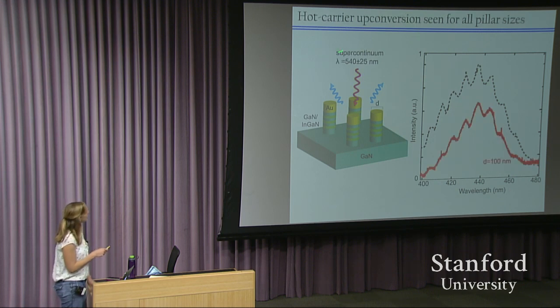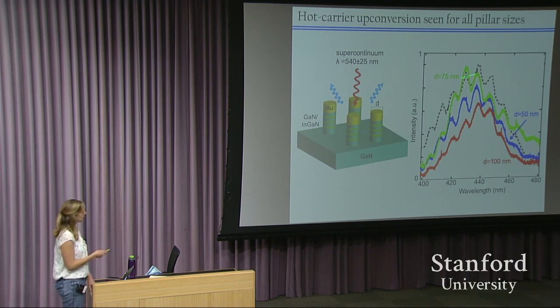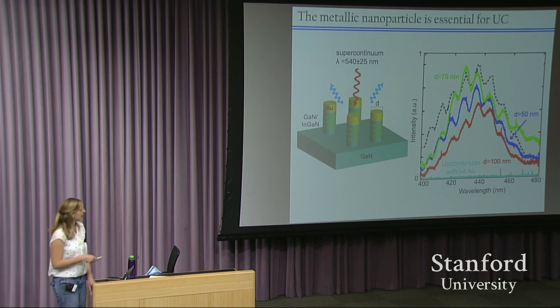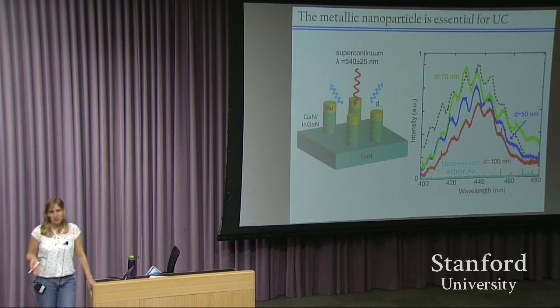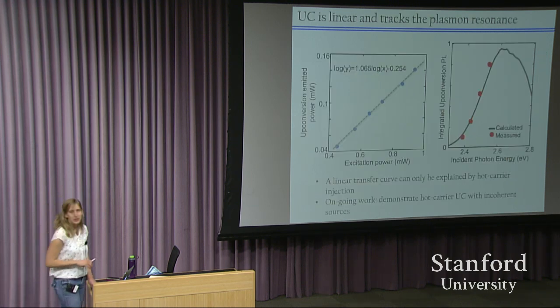And then we can shift our illumination wavelength to be below the band gap of this quantum well structure, so here at 540 nanometers. And when the pillars were 100 nanometers across, we saw clear upconversion that paralleled the photoluminescence. We could also tune the upconversion spectral intensity based on the size of nanostructures, so 75 and 50 nanometers. And then if we had no gold, there's no upconversion. So I think this is a pretty cool scheme for taking a non-upconverting material and making it upconvert simply by adding a thin metallic nanostructure on top.